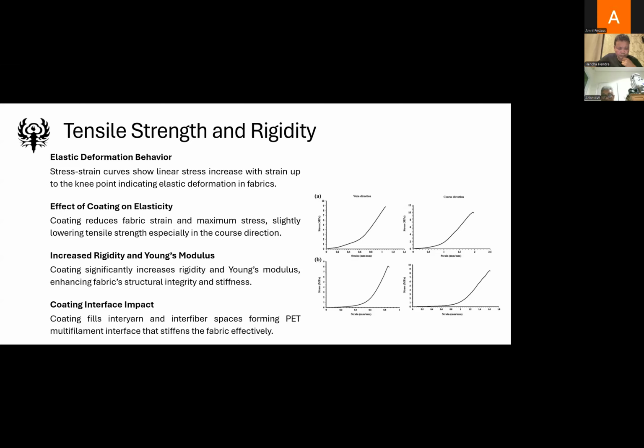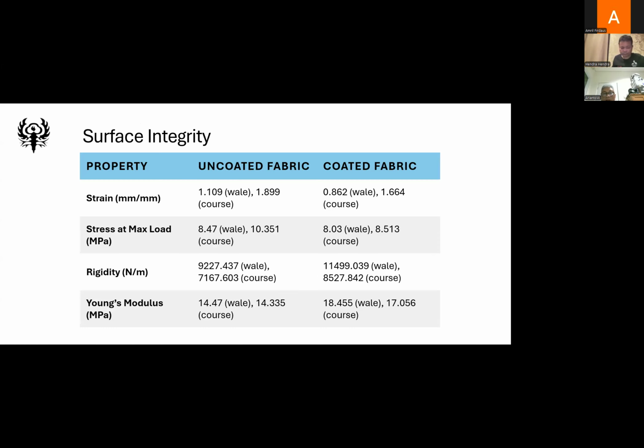For the coating interface, we can see from the SEM that the coating fills the spaces between the fibers, between the polyester multifilament fibers. Then for the second assessment, the surface integrity, comparing before and after coating, both stress and strength decreased a little bit, but the fabric is significantly more rigid, and the Young modulus also increased quite significantly.